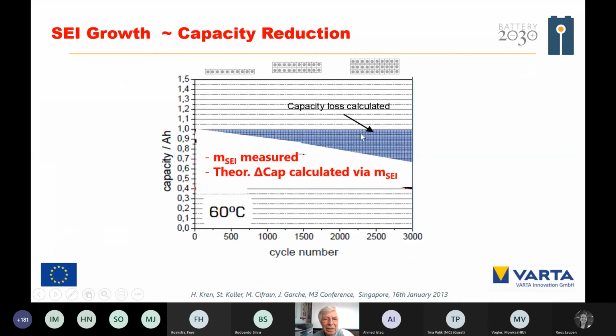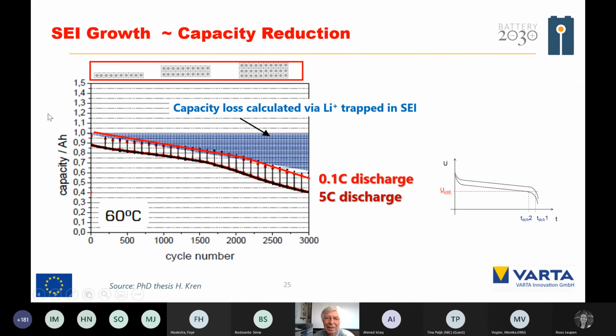And Harald Krehn from VARTA Innovation measured in his dissertation the mass of the SEI in the anode, and then he calculated via that mass of the SEI the theoretical capacity loss. And that is the result of the calculated capacity loss. And then he measured that. And you could see that here for the 0.1 discharge, the curve is nearly the same as the calculated one, because your SEI has grown.